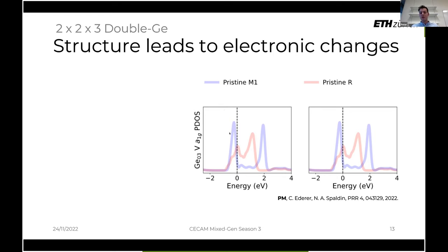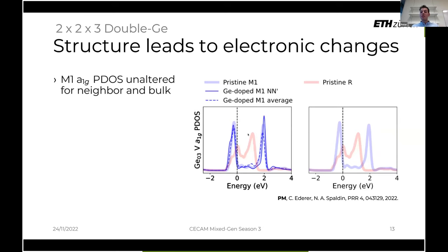And so previously, we had these thick lines, in blue the pristine monoclinic phase, and in red the pristine rutile phase. After the addition of germanium, we see the same behavior we saw in the structure. So we see that the nearest neighbor, which is the full line, retains its dimerized peaks. So there is a bonding peak and an antibonding peak. This remains very nice. And the same is true for the average, which is shown in the dashed line. So the average of all the atoms in the whole unit cell stays almost exactly the same as it was before.